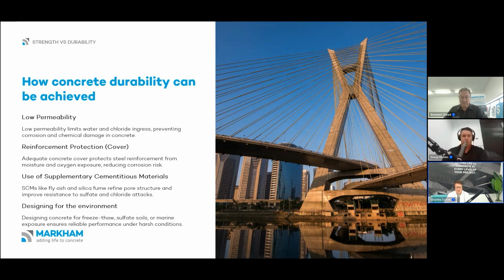We're seeing a lot of SCMs, supplementary cementitious materials, being used now, such as fly ash and silica. A lot of these are improving the resistance of the pore structure to prevent attacks over the design life of the concrete, and responding to the environment that it's in. A lot of attack from soils, marine exposure, harsh conditions of mining concrete, for example. So just bearing that in mind in the design of the concrete, the actual environment that it's going to be in.